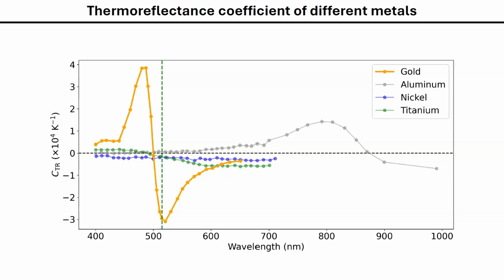But because you also mentioned that you can have some interference with the titanium, I don't know if you can use gold without the additional layer. I mean, eventually it would be better not to use titanium, yeah, because it has been shown titanium can react with the sample. And aluminium also. This I didn't know. Aluminium is a very reactive one, yeah. But that's why I was just wondering what happens if you do it without, yeah.